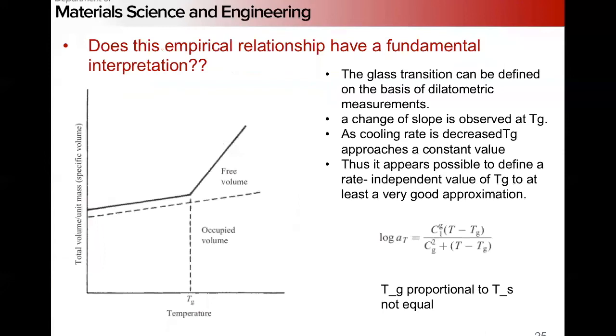Right? And so if we measure from dilatometry, our thermal expansion as a function of temperature, remember, we see a change in slope near the glass transition. And of course, the faster the cooling, the less well-defined this point is. At higher cooling rates, this is much more of a smooth curve than an actual sharp point. But if we cool it slow enough, this TG really does approach a given point.